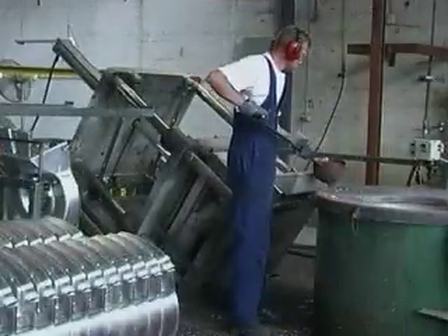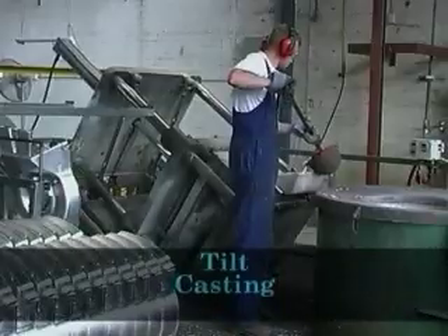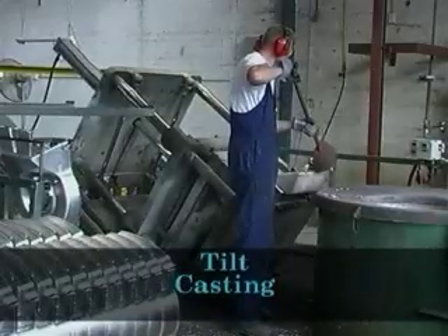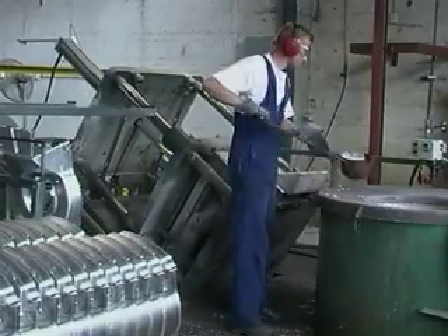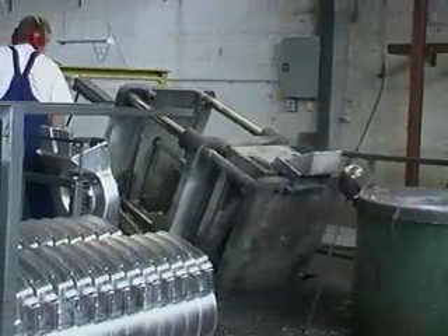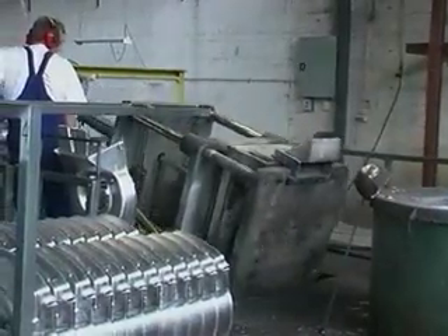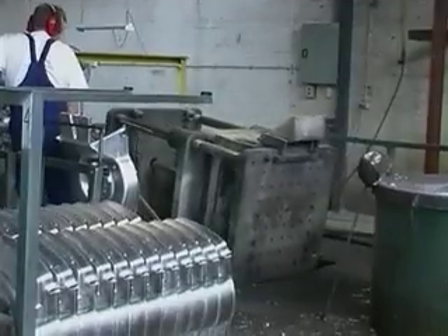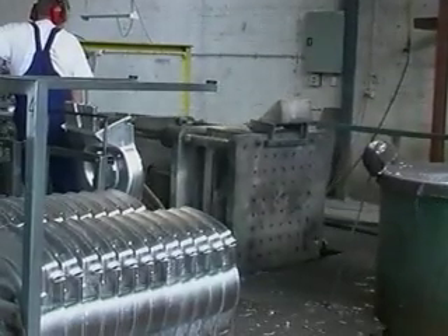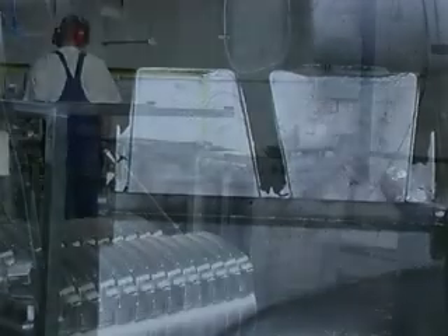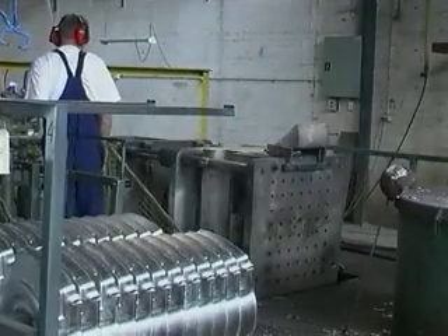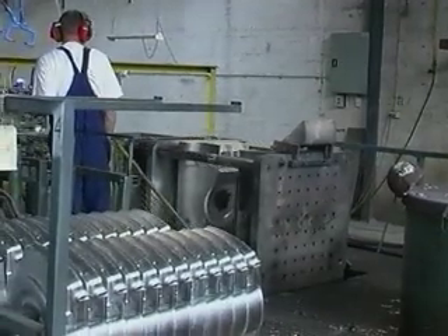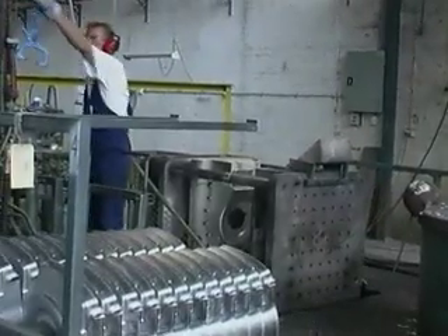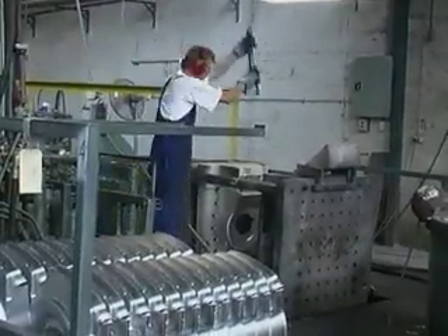An important modification to gravity die casting is tilt casting. Molten metal is loaded into a trough called a launder. The die is gently tilted back, causing the metal to flow smoothly out of the launder and into the die. With tilt casting, the runners and risers can often be kept small. In this case, only 20 to 30% of the metal cast needs to be recycled. After 3 minutes, the aluminium alloy has solidified. The die opens and the casting is removed.